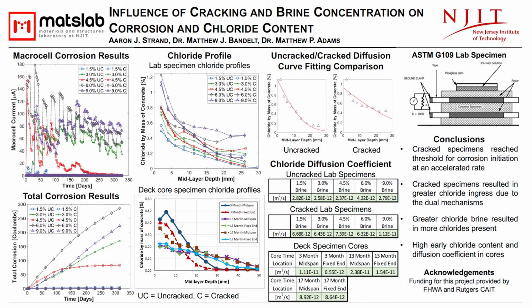The presence of a crack results in a macrocell corrosion value that exceeds the threshold to initiate corrosion of the reinforcement at early ages if sufficient chloride is present. This correlates to literature in measurement of chloride in bridge decks, where the early age presence of cracks within a concrete deck resulted in higher rates of corrosion.